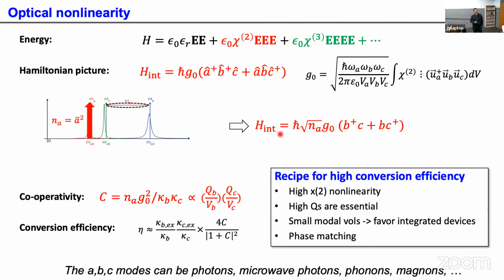The figure of merit is often described by this cooperativity, which is really the exchange rate between the B and the C mode divided by their loss. That is eventually determined by the quality factor of these two coupling modes and the mode volume. Again, it's Q over V, Q over V. So you really want to make a smaller device to improve your Q over V, like Purcell factors.